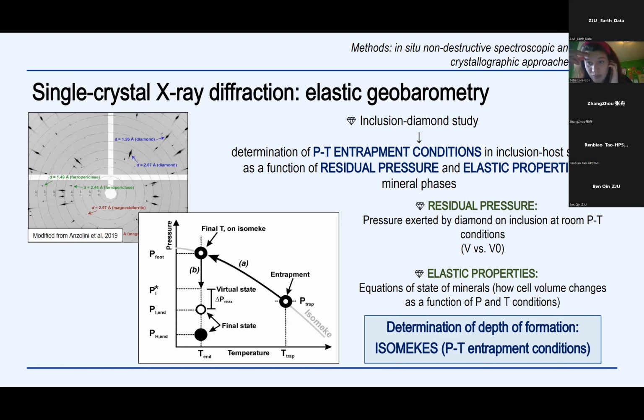Combining these two elements, through elastic geobarometry we are able to determine and calculate the so-called isomekes. The isomekes are P-T curves in which each point corresponds to the P-T conditions at which the volume of the inclusion is equal to the volume of the cavity of the host that contains this inclusion.